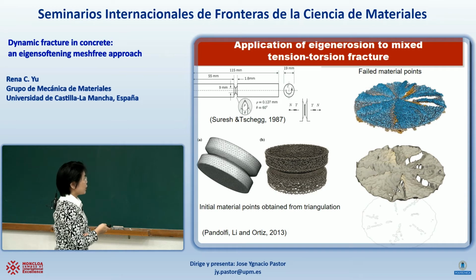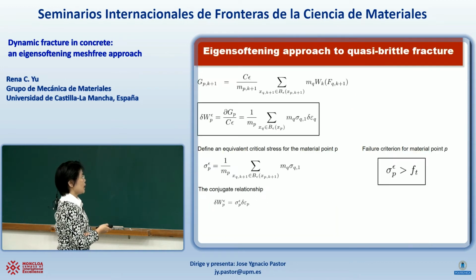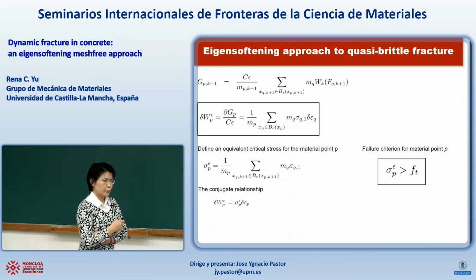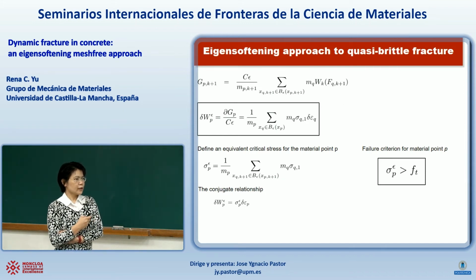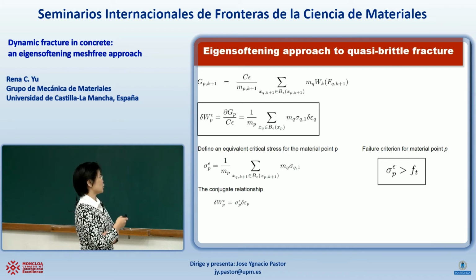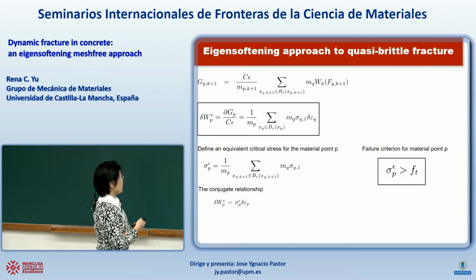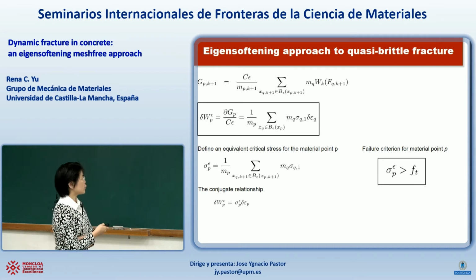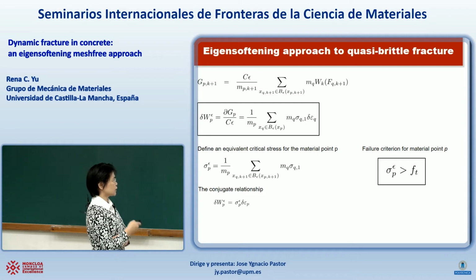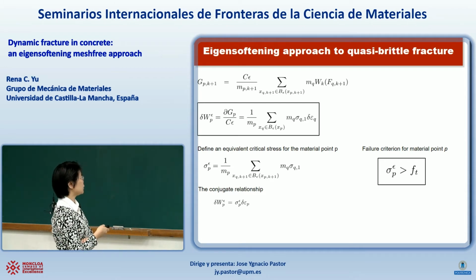So since we want to apply this approach to concrete, and we know that concrete is a quasi-brittle material, we do not expect that the eigenerosion approach was going to work, at least work perfectly. So we developed, with respect to the equation that I have shown before, this is the energy release rate. We work on this equation. We try to get the incremental strain energy, because later we want to use a stress criterion instead of the energetic criterion.